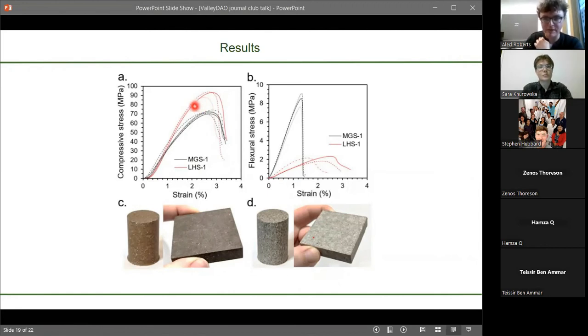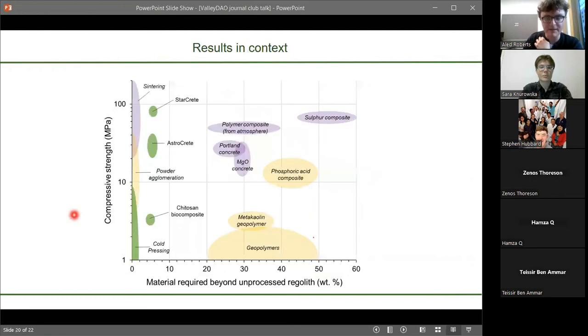And just to put that into context, this is a diagram comparing other technologies for potentially building on the moon and Mars. As you go along this axis, you need more material beyond unprocessed regolith. So you want to be down here. You want to use as much raw moon dust or Mars dust, and as little of whatever else as your binder as possible. And then obviously compressive strength, you want to be as strong as possible. So we're up here in this corner, which is a low amount of binder to add and quite high compressive strength.